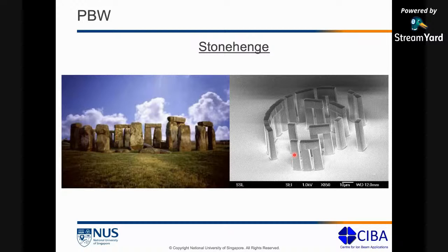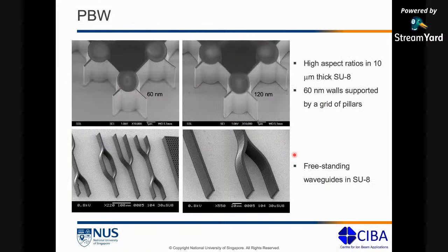But today, what we actually use proton beam writing for is to create these kind of high aspect ratio structures. Okay, so this was done in a 10 micron thick SU8. So you can see how high the aspect ratio is. So this is 60 nanometers and this is 10 microns deep. So if this is 60 nanometers, that means the focused beam spot that they got has to be much smaller than 60 nanometers, right? So they were literally pushing the beam line to its limit to get these structures.